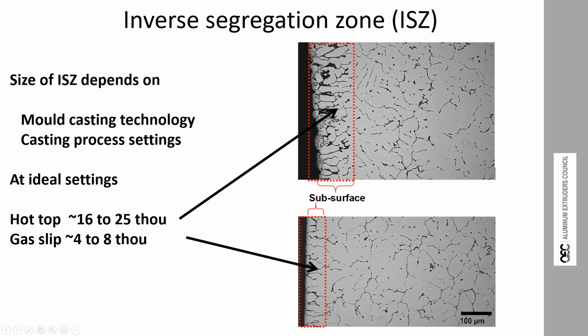Now, the size of the inverse segregation zone depends a lot on the casting technology of your billet supplier. These are the 2 most common casting technologies visible in North America at this time. The top one here, hot top, known as Numax or MaxiCast from Wagstaff. The inverse segregation zone tends to be bigger, and notice the black patches in here, there are more of them. It's also richer.